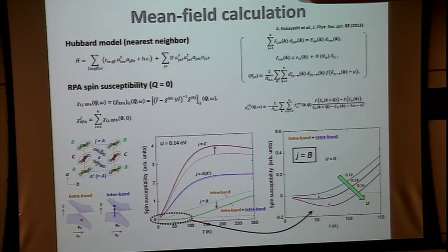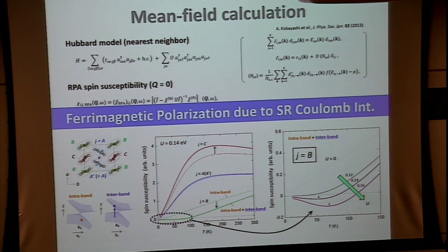And this behavior is completely reproduced by the mean field calculation of the Hubbard model. So as U is increased, only at the B site is the spin susceptibility negative, and such a situation occurs. And this is due to the cone being tilted. Okay, the A site and C site show conventional behavior, but only the B site shows strange behavior. So this ferrimagnetic spin polarization is due to the short-range Coulomb interactions.